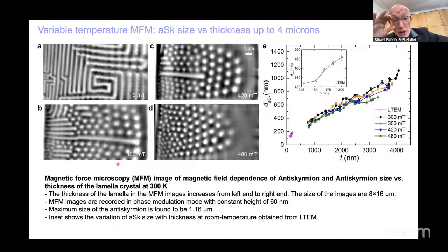So totally different from Lorentz. Lorentz measures the in-plane components of magnetization. Here we're measuring the out-of-plane stray field, and they look like simple objects. And again, we found that the diameter of these antiskyrmions increases with the thickness of the lamella in which they're imaged. And the reason for this is because of the role of the dipole-dipole fields. We demonstrated a very important effect: in thin layers they suppress the size of these objects, which otherwise are much larger. So for thicker lamella, these objects become microns in size, and we can detect them optically.